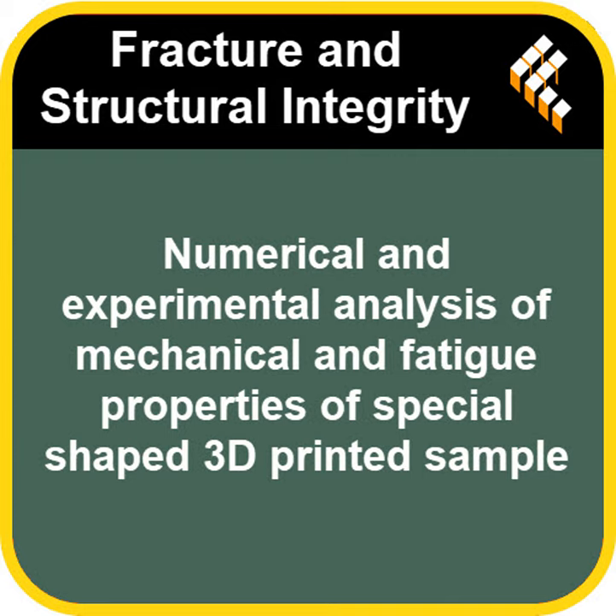The success was actually quite remarkable. Not only were the overall curve shapes and the maximum load values very similar between the single experiment and the calibrated simulation. Which is already good. Right. But even more crucially, the numerical model accurately predicted the physical mode of failure, where and how it broke. That's the critical part, isn't it? Predicting where it's going to break under load. It absolutely is. The post-test photograph clearly showed the sample physically separated right at the junction where the inner and outer structures of the complex geometry met. And the numerical model had predicted that exact failure point. It did this by identifying the location of the maximum or critical equivalent plastic strain.